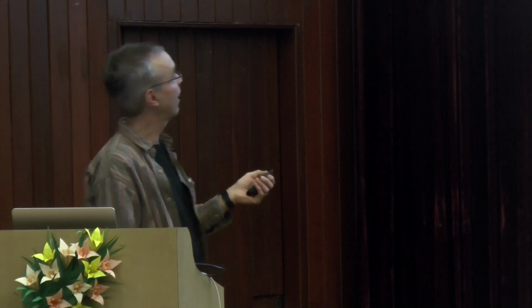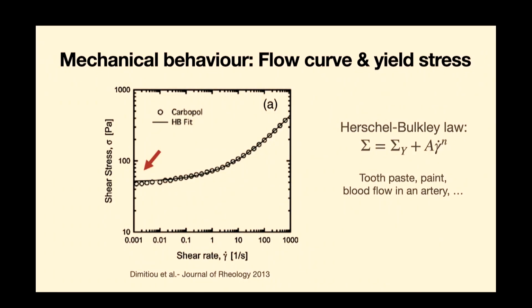Okay, so if we look at mechanically perturbing these systems, one standard protocol is to just make them flow. So you put your material between two plates and you do steady shear. Okay, and the result is what's called the flow curve, which tells you how the shear stress that you need to apply relates to the shear rate, so the speed at which you're moving the top plate in essence. Okay? And what you find in a large variety of these amorphous materials is that the flow curve is not what you would get for a Newtonian fluid, so the stress is not just a linear function of shear rate, but actually you get something called a yield stress, so you need a non-zero stress to move the top plate even slowly. And then beyond that, the way the stress increases is typically given by a power law in shear rate. Okay? This is called the Herschel-Bulkley law.